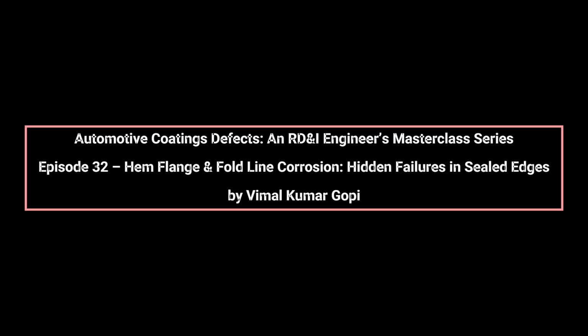Once moisture enters a hem flange, capillary action holds it in place. Unlike flat panels where water can evaporate, hems remain wet for extended periods. This prolonged exposure accelerates electrochemical reactions. If zinc-coated steel is used, sacrificial protection delays rust formation. But once zinc is consumed locally, corrosion progresses rapidly into the steel substrate. Aluminum hems face different challenges, including filiform corrosion and oxide breakdown under trapped moisture.